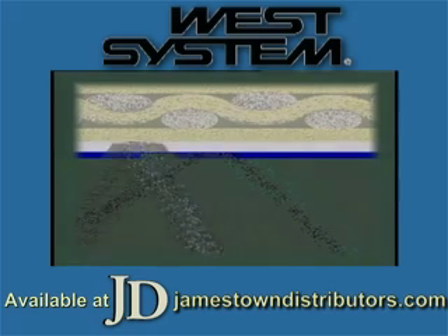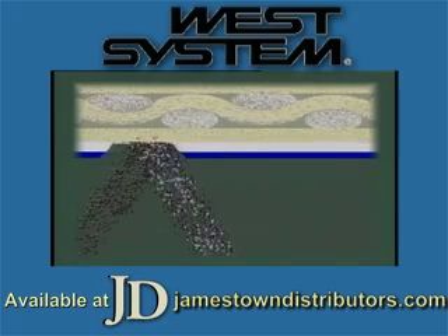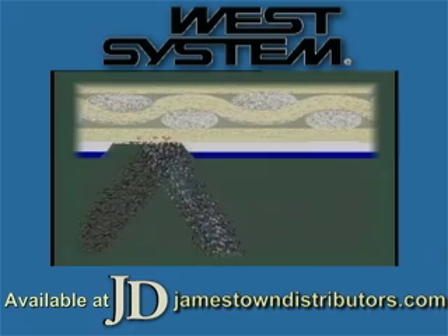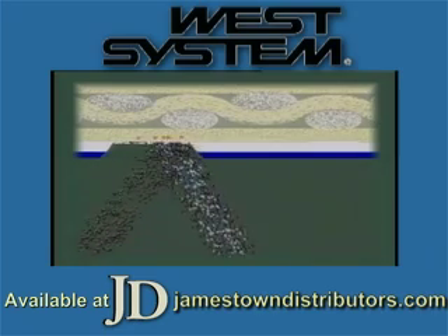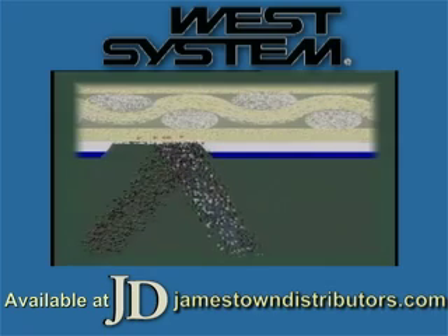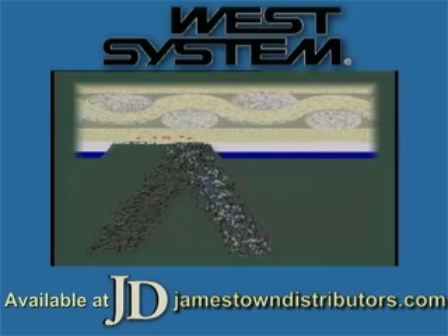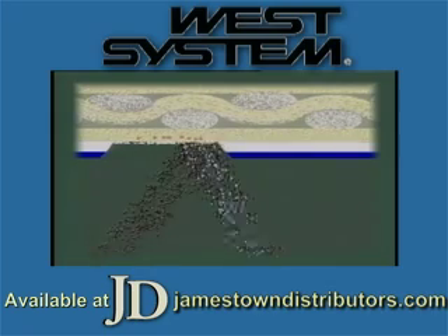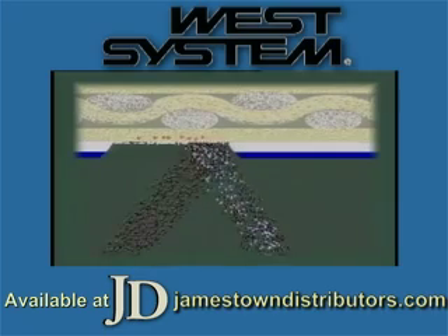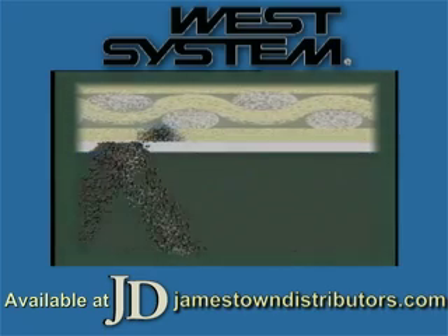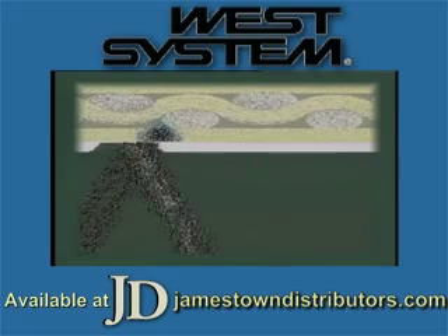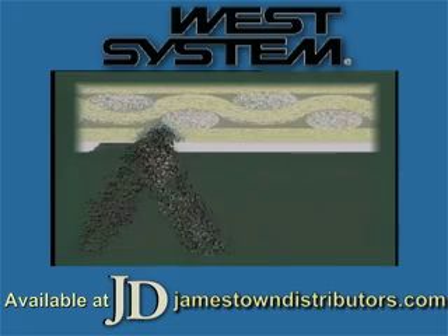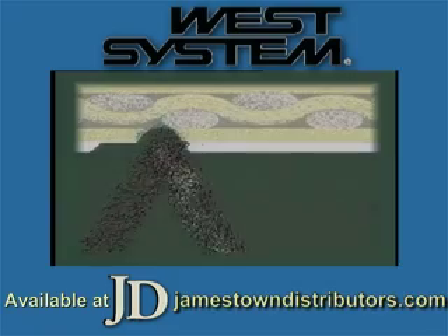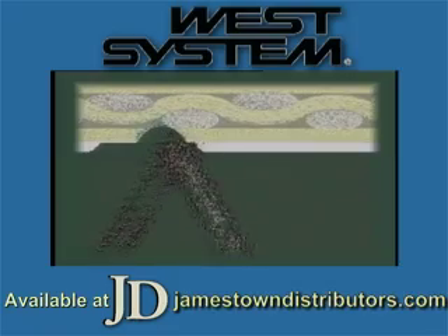If you use sandblasting to remove gel coat, use a 2-step method. First, lightly blast the antifouling paint off. If you attempt to blast antifouling paint and gel coat at once, you'll see the pigment fly away. But small particles of copper from the paint will embed in the laminate and act as a contaminant, creating bonding problems later. So after lightly removing the antifouling paint, blast the gel coat. This will open any hidden voids.